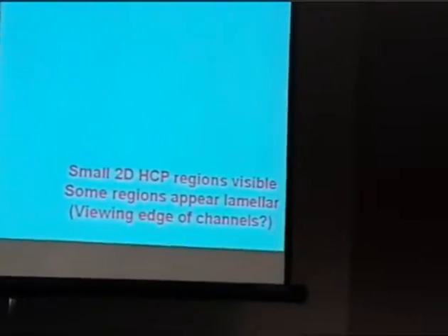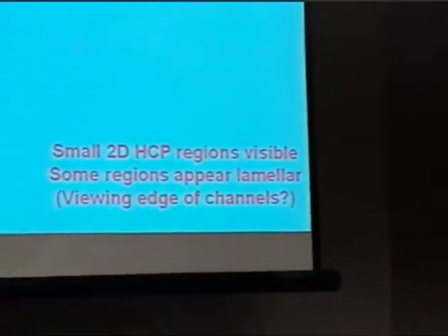So that's kind of consistent with the pore size that we got from nitrogen adsorption, although it means that we have walls that are only about 0.7 nanometers thick. And that's relatively thin for these materials, but it's not out of the range that's been observed for other materials. And the final evidence that we have that they have the 2D hexagonal ordering is from TEM.